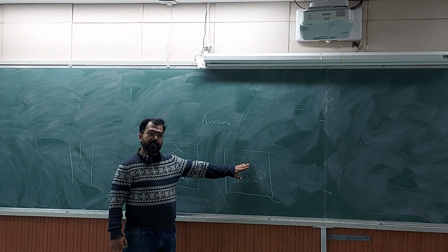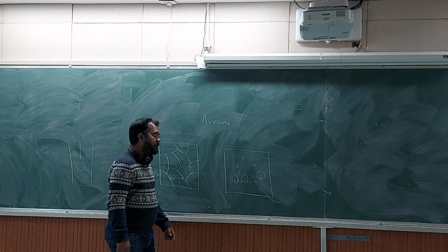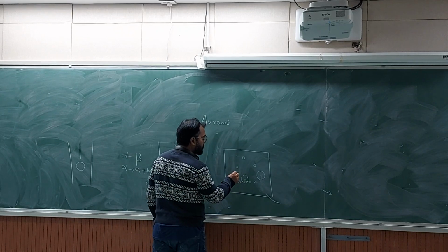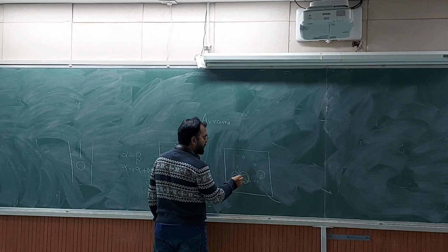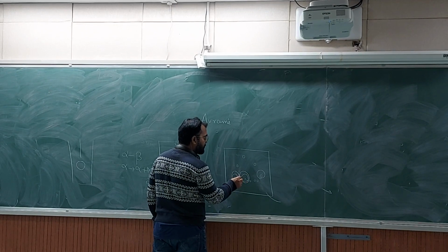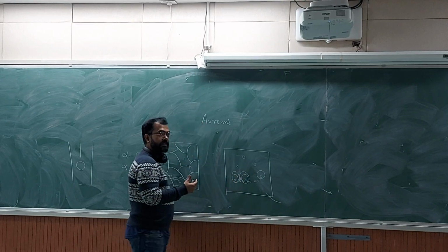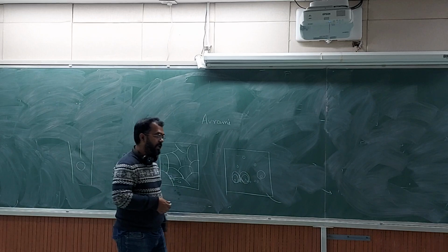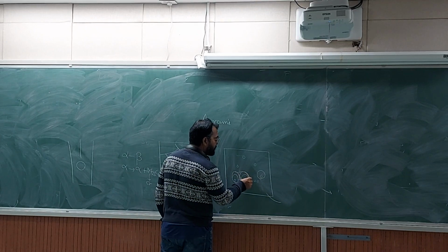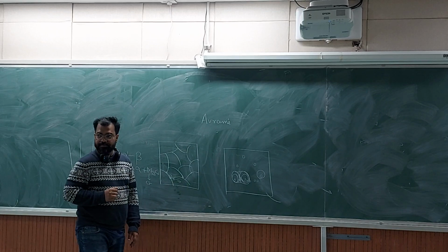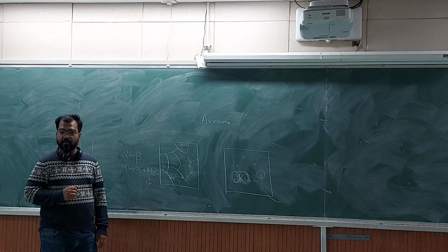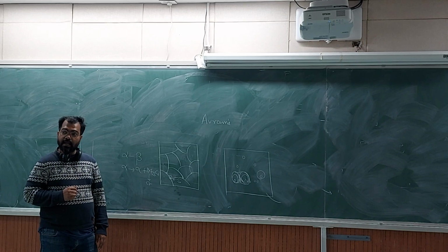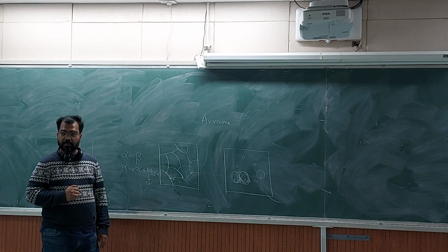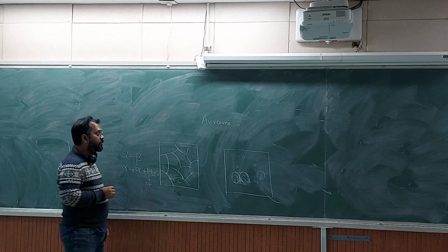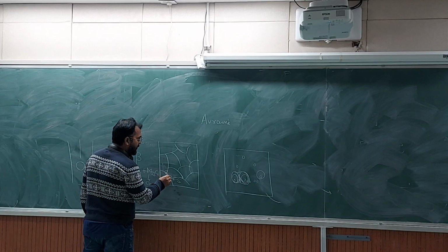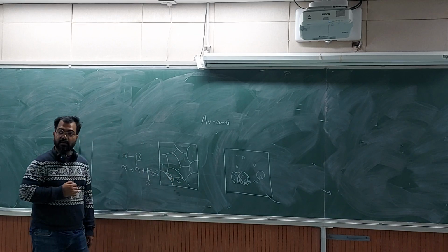Okay, and then there is a void coalescence. So two voids will grow to a very large size, and then the material which is intact between them acts as a tensile sample. And then it breaks at UTS, and then these two will become one bigger void. This part is not happening in precipitation. So we don't have two precipitates which are growing and joining the two. That is not happening,